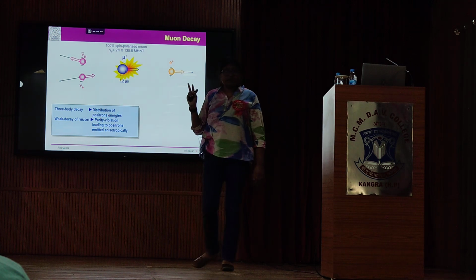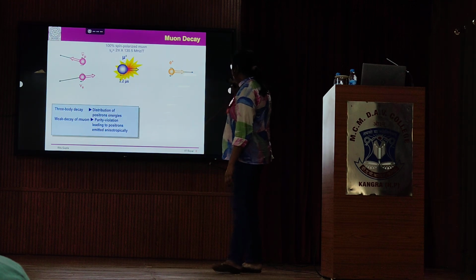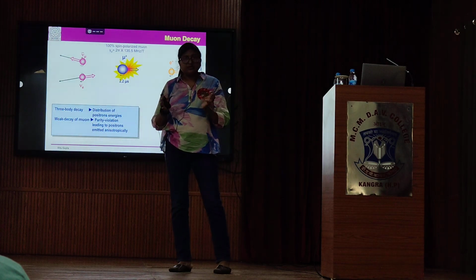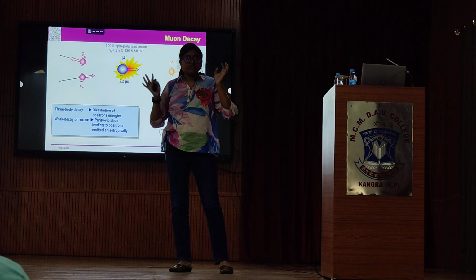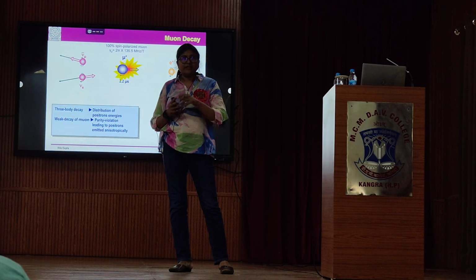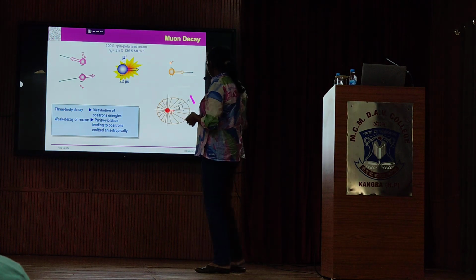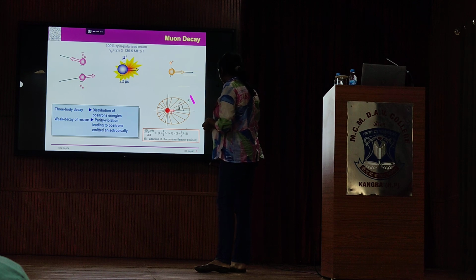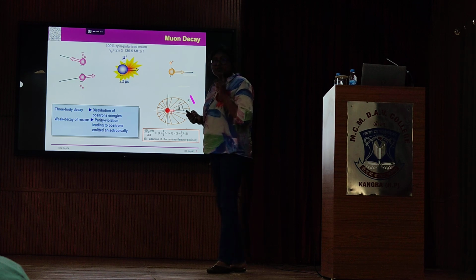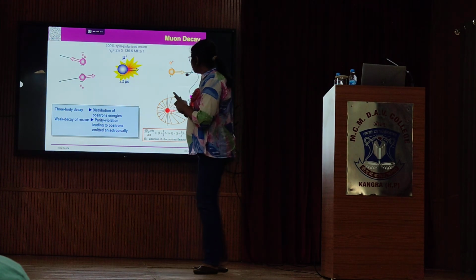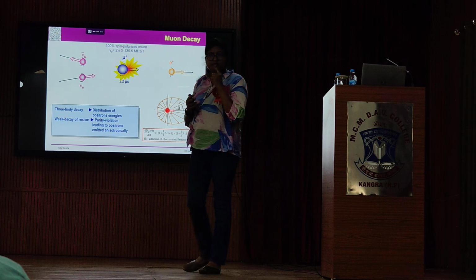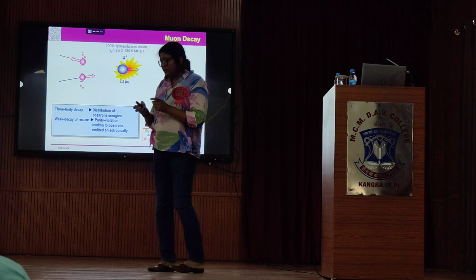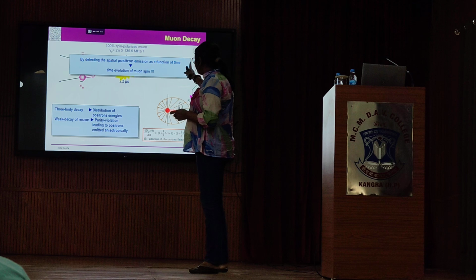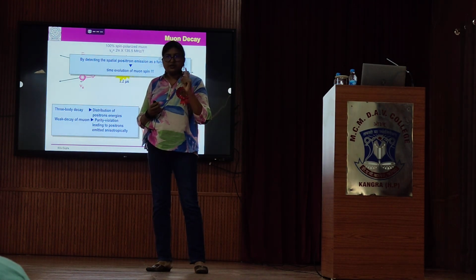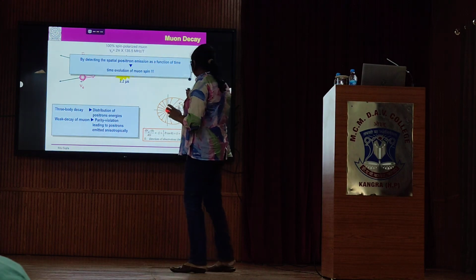And since this is a weak decay, there will be a parity violation, and because of that parity violation, the positrons which are emitted from the muon decay will be emitted anisotropically over the solid angle. Okay, and that anisotropy one has to measure. These things I am not going into much detail. Also, if you look at the muon spin at any point of time, this will be along the direction of the positron emission at that particular point of time. So that means by looking at the spatial positron emission as a function of time, you can basically probe the spin of the muon as a function of time. Okay, so this is what this experiment does.